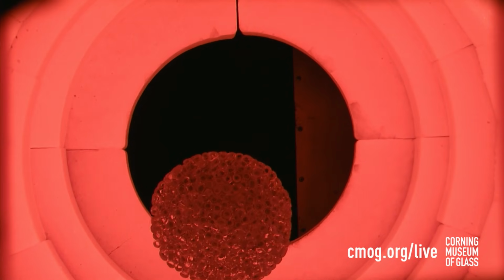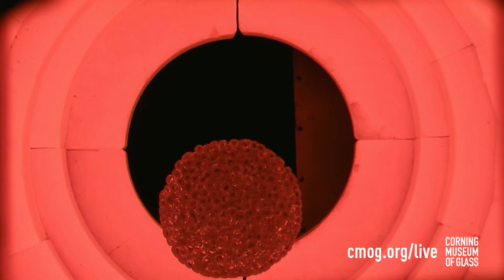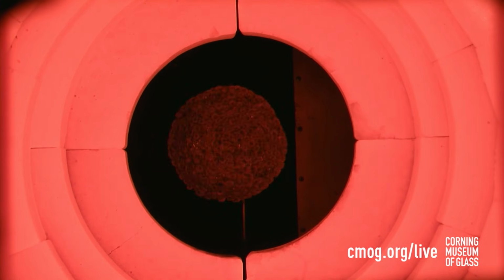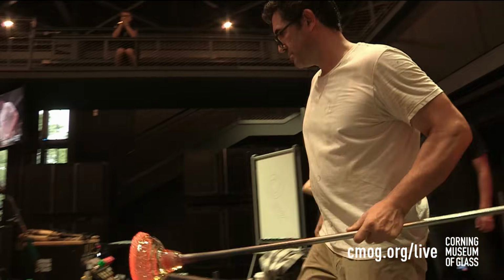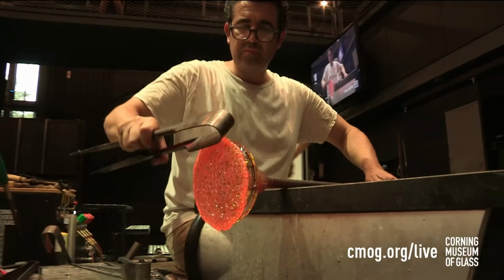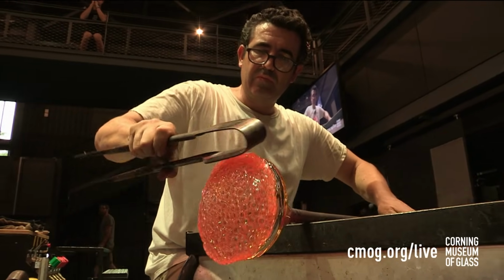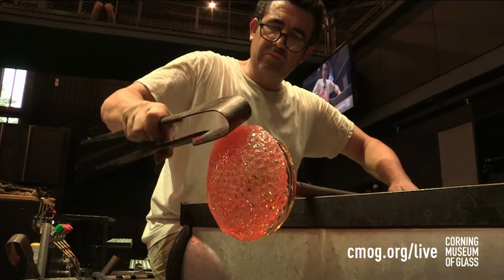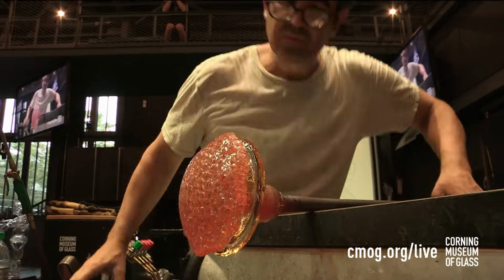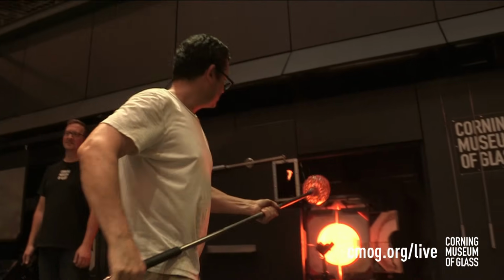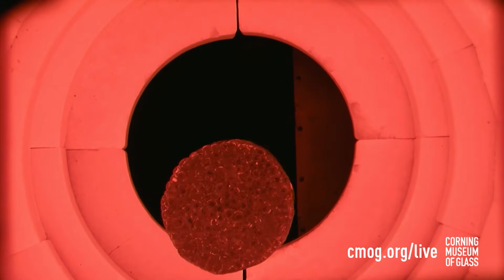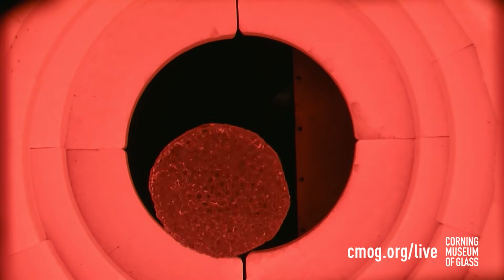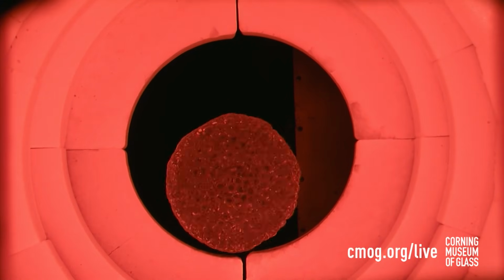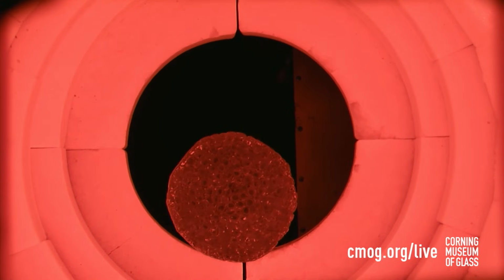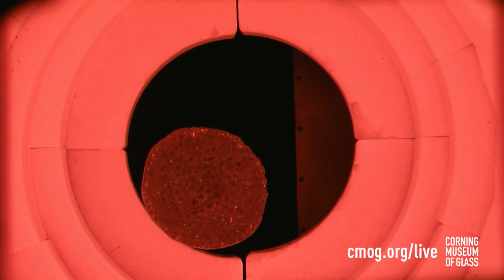So for instance, our glass is a soda lime glass. It's one of the more common types of glass that you run into. It's what these windows are made out of. If you're wearing glasses, it's what your lenses are probably made out of. Now, soda lime glass is silica sand. Silica is the main ingredient in all glass. It's also the main ingredient in beach sand. But silica, soda ash, and limestone, those are the three main ingredients in our soda lime glass. Now, soda ash is our flux. That's what tells our glass to melt at about 2,000 degrees Fahrenheit.